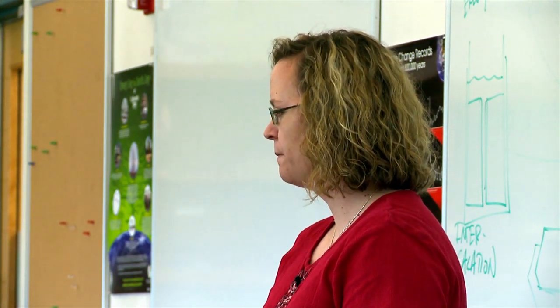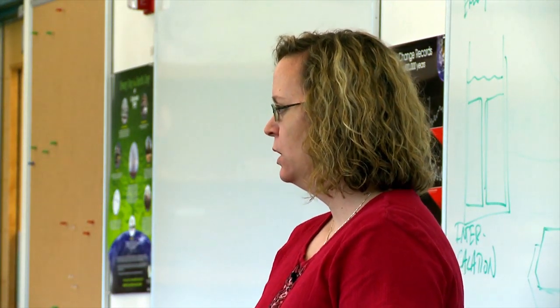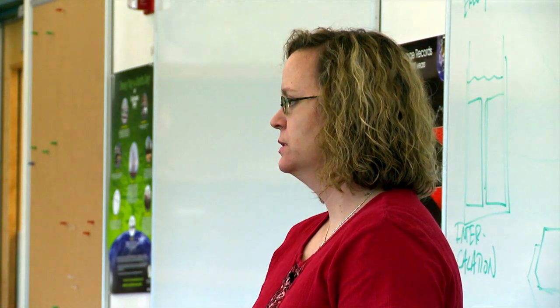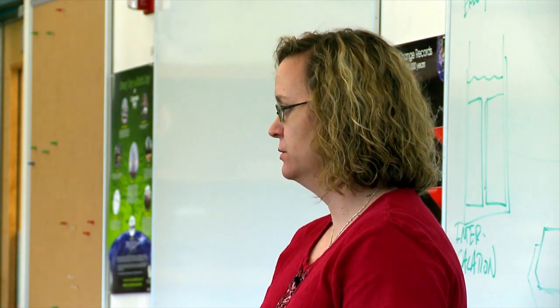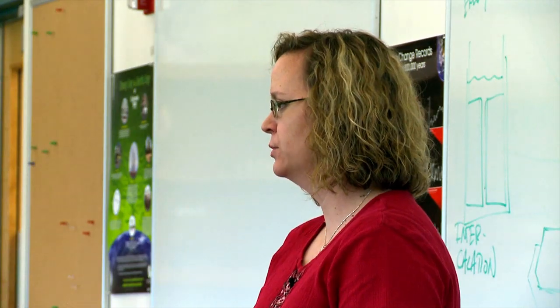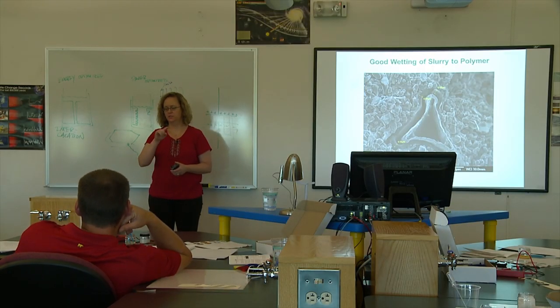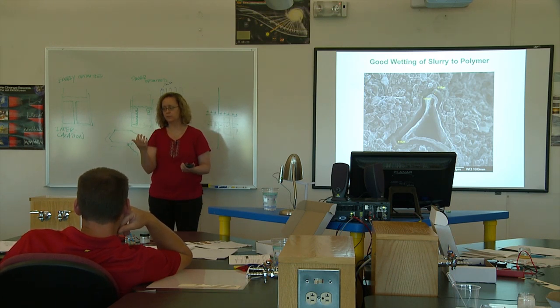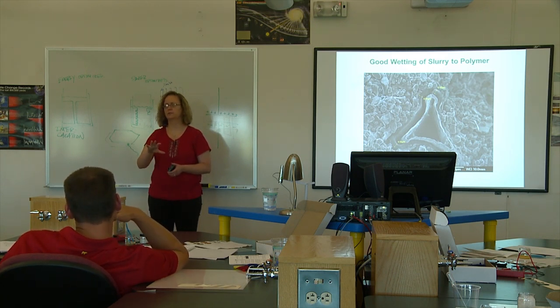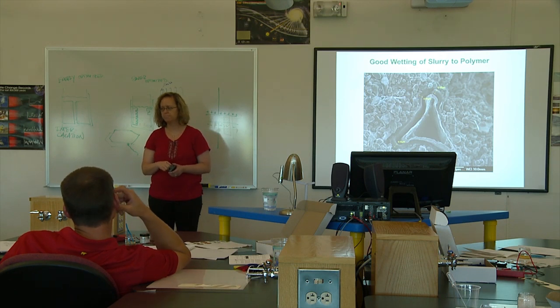So what's your polymer made out of now? And what are you testing or hoping to use? We took some inspiration from flame retardant materials, and then we added a backbone. So that's the backbone of the polymer. Then the side chains we added, we actually took some from a compound that's a very common laxative for infants that has some good oxygen groups that are thought to help lithium ions move. And then we added in another monomer that is known to be mechanically very flexible. So we've mixed and matched a bunch of different things. They're all covalently bonded. They're all attached to the same polymer, but we.